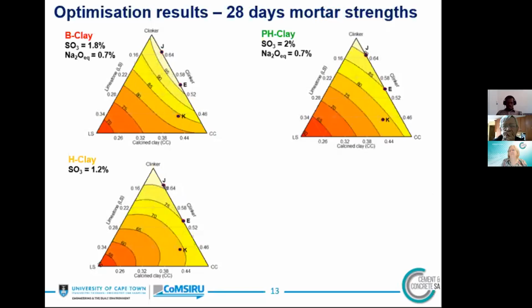Now, with these two adjustments, sulfate and the alkali content in all the mixed proportions, it's only now the amount of clinker, amount of calcined clay and limestone that control the reaction. Now, this figure here shows optimization of results at 28 days. You can also see the required sulfate for each of these mixed proportions.